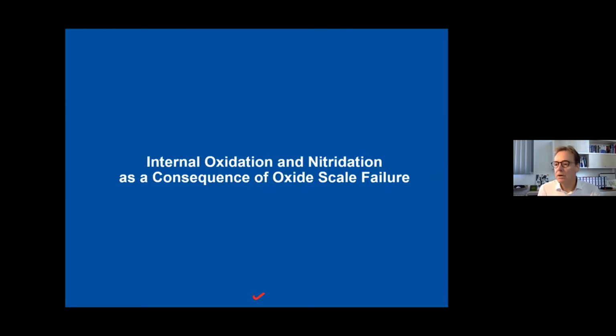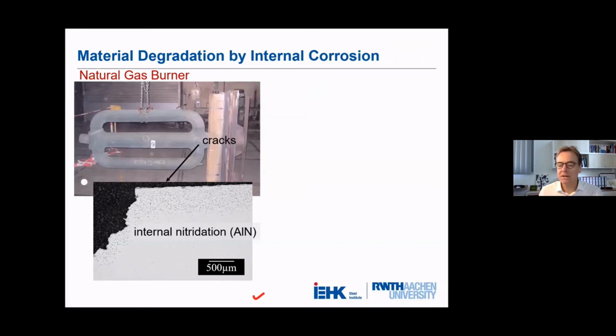Well, in most technical applications we observe both oxidation and nitridation simultaneously, and often failure of a protective scale leads to internal attack. Here are two examples from technical failure cases. First, a broken natural gas burner, where we had a large crack, and then this complete burner was broken and not working anymore.